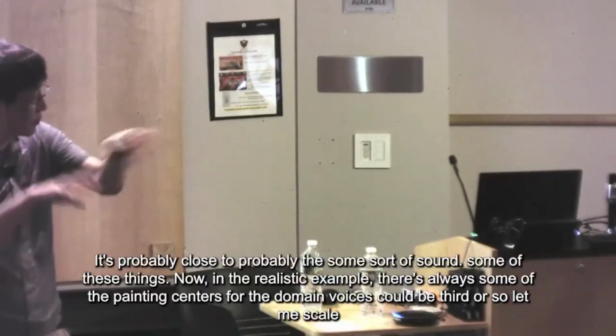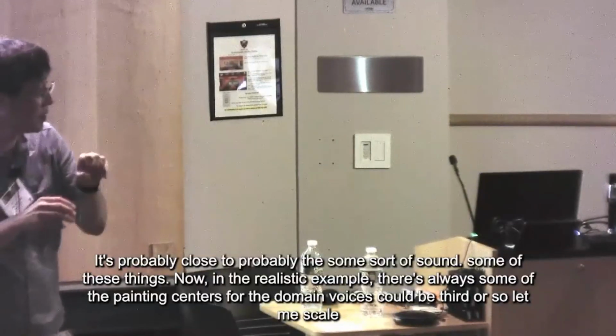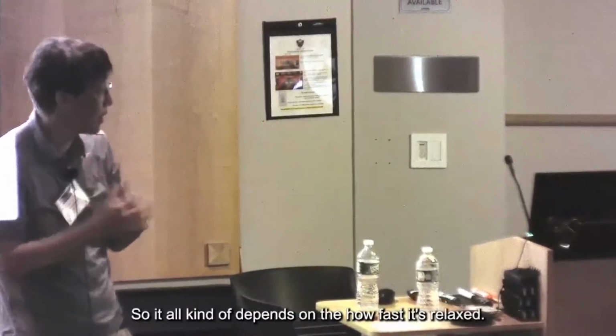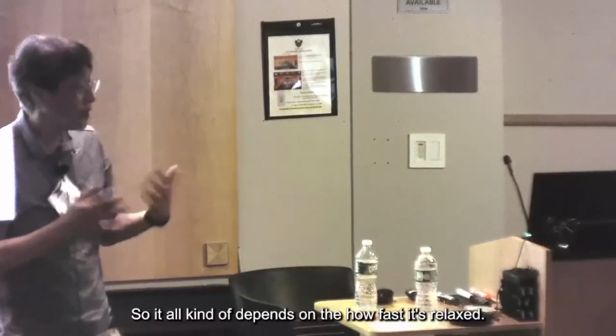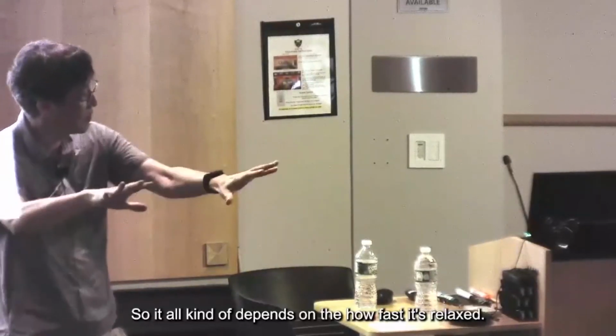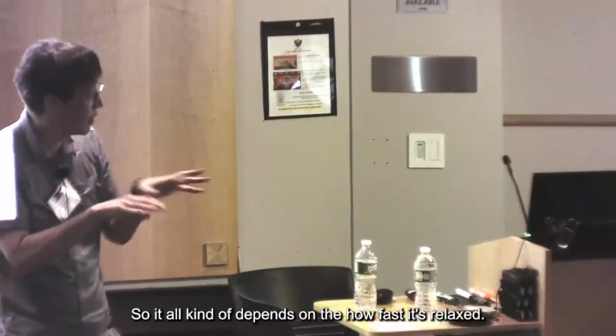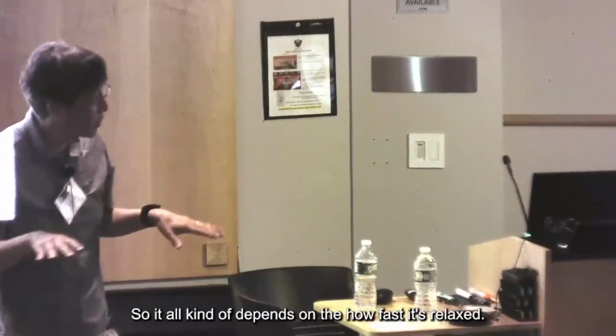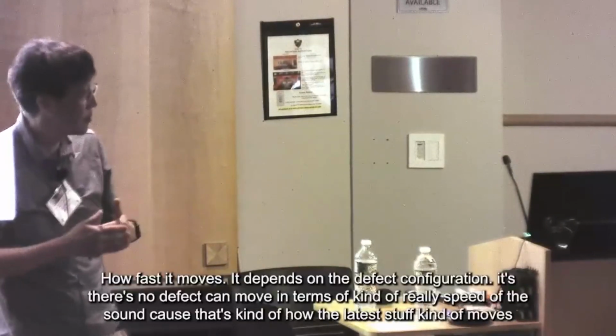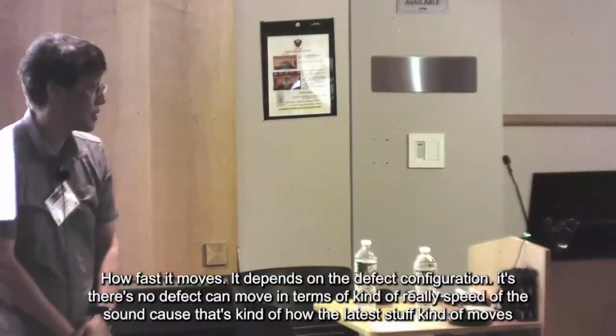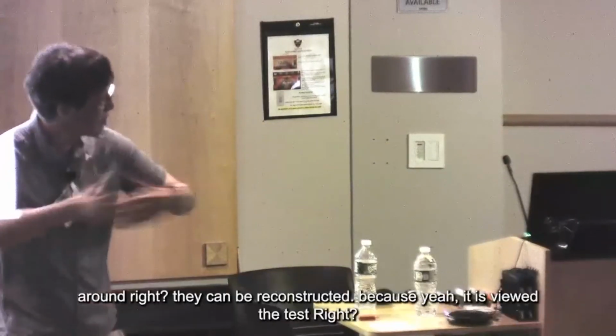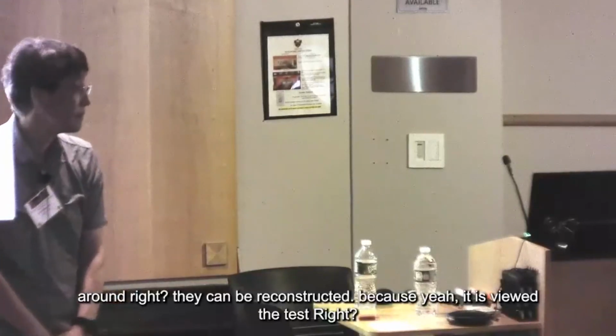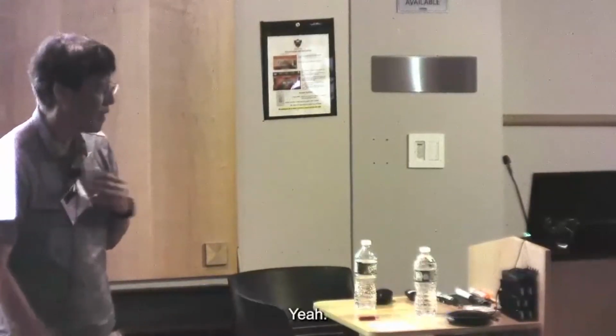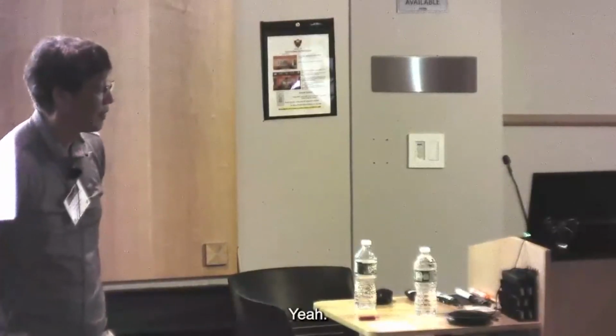Now, in a realistic sample, there are always some pinning centers for the domain walls. This could be dirt or some atomic-scale defect that will slow down the domain wall motion to slower than sound speed. So it all depends on how fast it relaxes and moves, which depends on the defect configuration. If there is no defect, the domain wall can move at really the speed of sound, because that's how the lattice moves around. So they can be reconstructed in just seconds. Yeah, it's really fast, right?